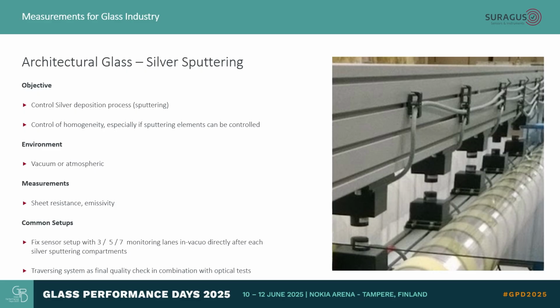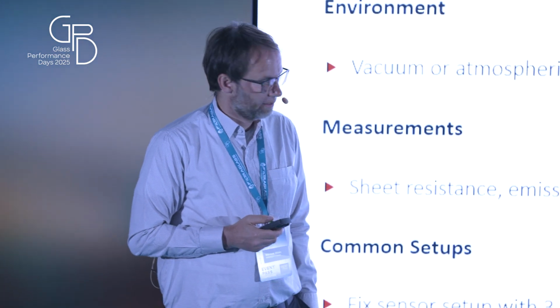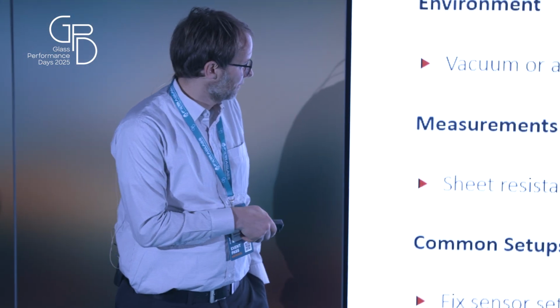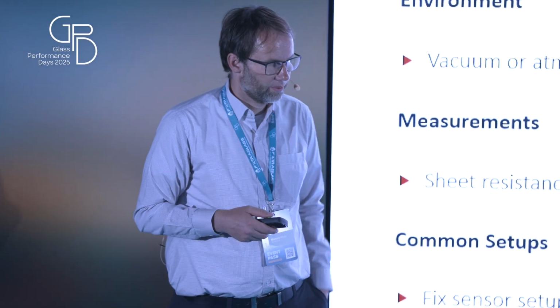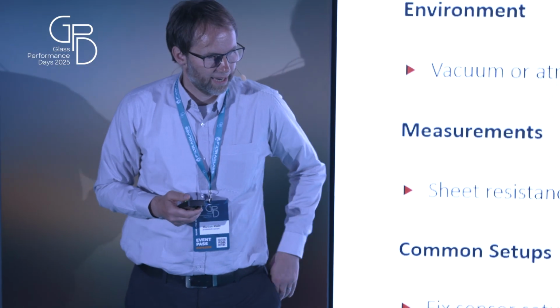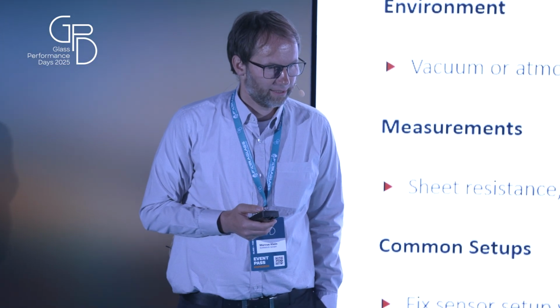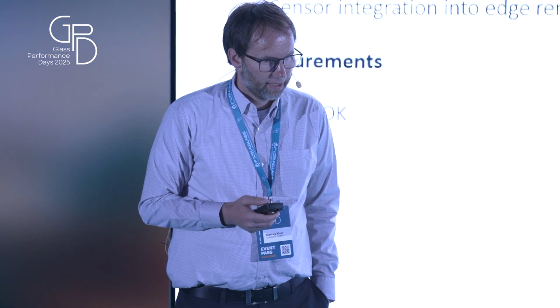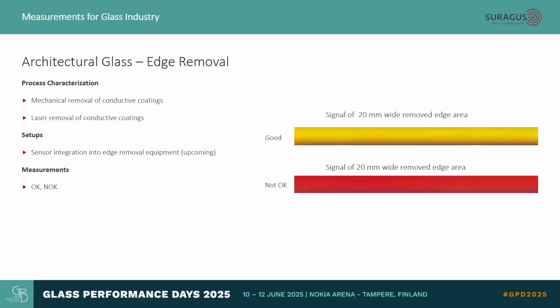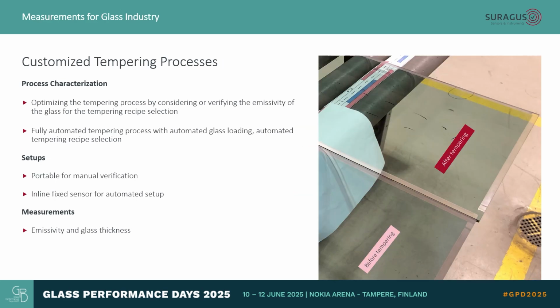in the vacuum. But very often there's also a final inspection, mostly together with an optical system to scan the final inspection of the total glass of the coating stack. Another application is edge removal or glass inspection to make sure that all the conductive layers have been removed. That's one application. Another application is to measure before and after the tempering process.